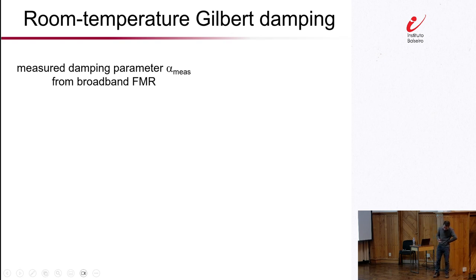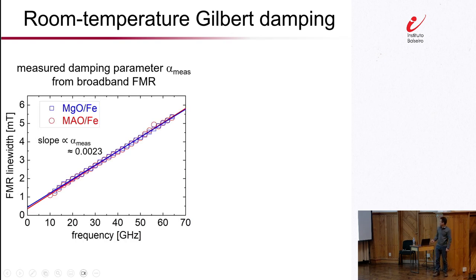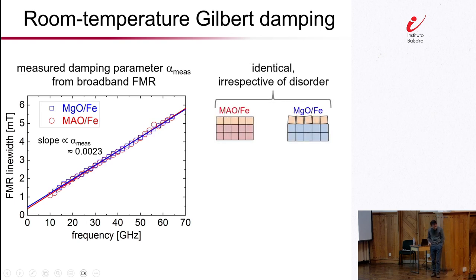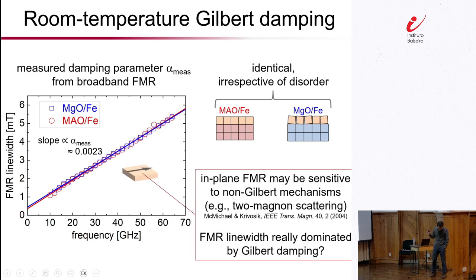Okay, so I'll show you first of all what we observed at room temperature. Using this FMR technique, measuring the FMR line width as a function of frequency and paying attention to the slope, the slope as a measure of the Gilbert damping parameter. Quite surprisingly, what we saw is that there's actually no difference. They have essentially the exact same damping parameter of about 0.0023. So this is quite surprising. This is indicating to us that irrespective of the crystalline disorder, we are ending up with the same amount of Gilbert damping. Quite odd. Now, having said that, there's sort of a small technical caveat.